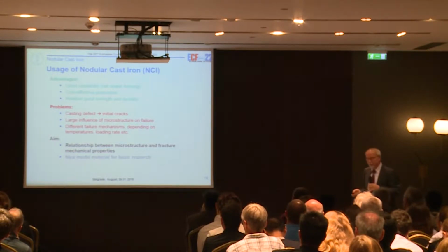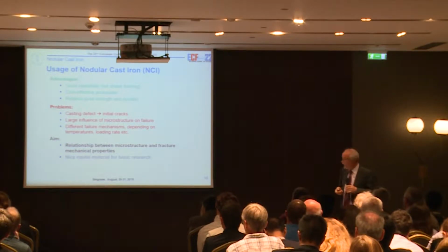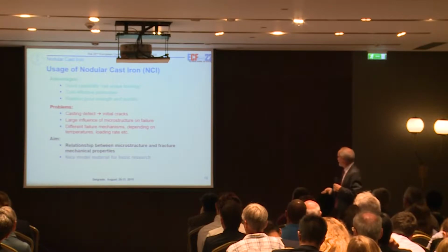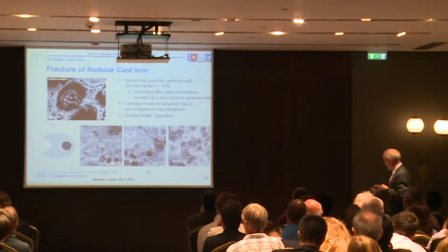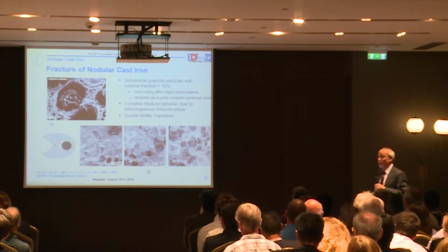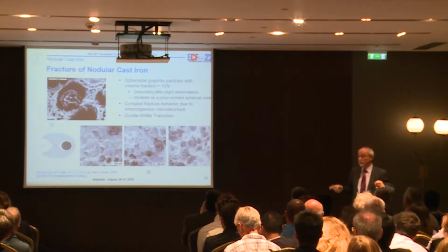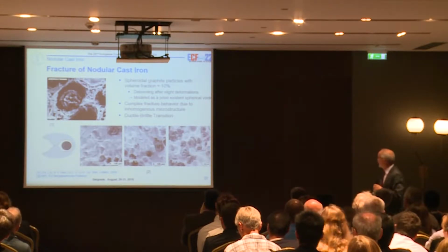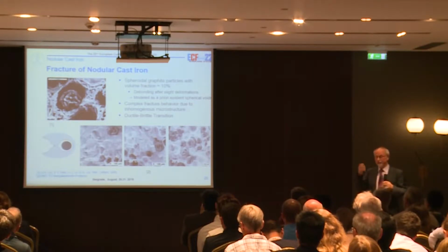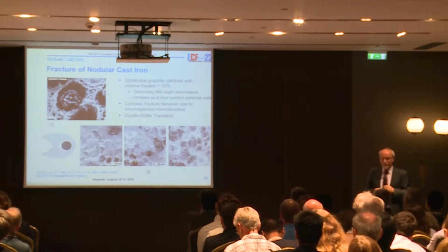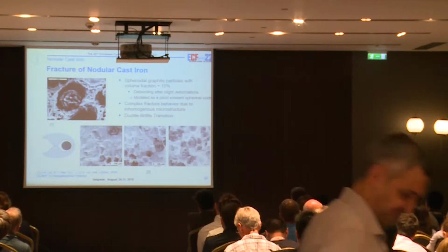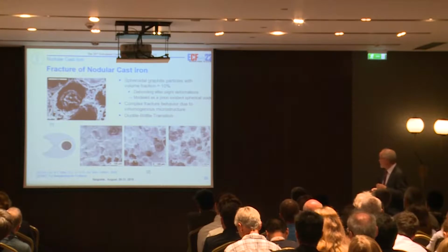And the other thing, we like this material as a nice model material. Why? If we look at the microstructure, we have about 10% volume fraction of graphite. Here, nodular graphite. And after deformation, it easily debonds, so we can omit it, so to say, in our simulations. We can consider it as voids from the beginning.